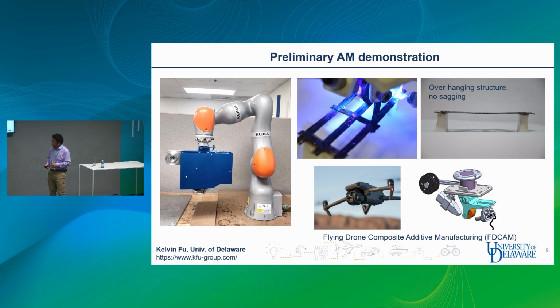And also my lab worked with my startup. We have developed this very small towpreg 3D printer that can print dry carbon fiber with epoxy with the help of our dual cure resin coating system in between. That shows we can print a small scale overcrossing bridge structure, so there's no sagging in between. So we think that we may use this technology for some civil applications. So now my lab is working on this flying drone composite 3D printing system.